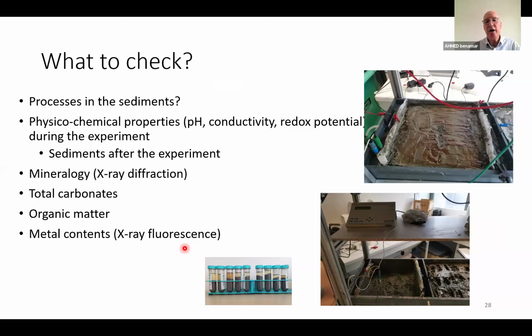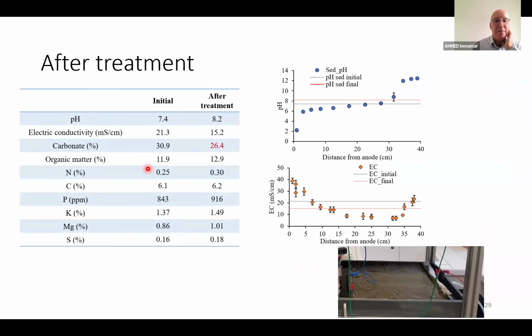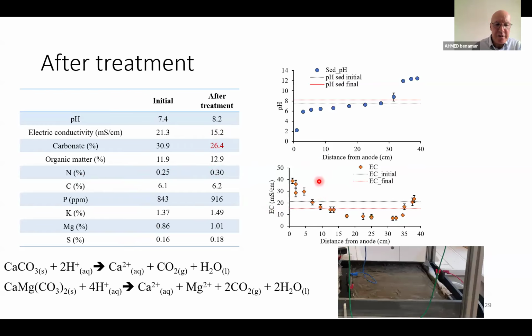So we had to check the processes in the sediment, where each process happens in the sediment during treatment. We looked at physical-chemical properties, pH, conductivity, redox potential during the experiment, and the sediment after the experiment: mineralogy, total carbonates, organic matter, and metals. After treatment, we see that only the carbonate decreased. There is no change in the other parameters, especially in elements like nitrogen, carbon, phosphorus, potassium, magnesium, and sulfur. Only the carbonates, because of oxidation in the anode parts, were partly dissolved following this reaction.